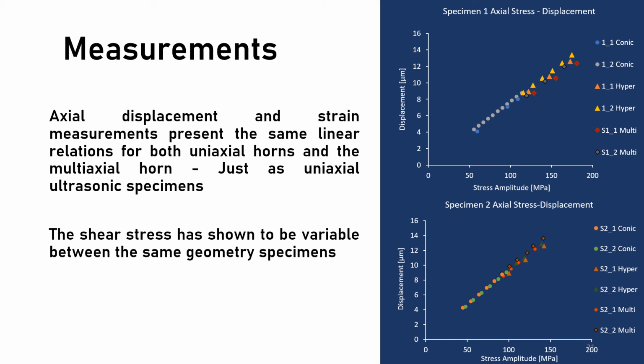We can clearly see that the axial displacement and axial stress have a linear relationship between all horns and in all specimens. Now, looking at the shear stress, they still have a linear relationship, but they present a different amplitude between different and same geometry specimens.